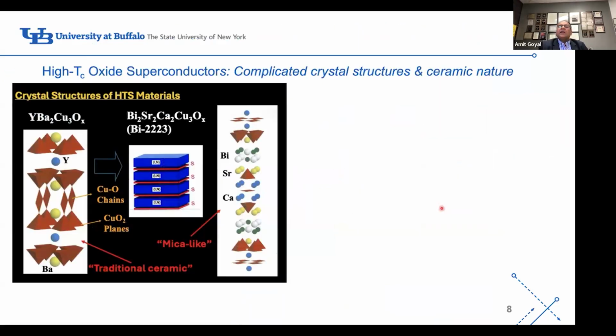Crystal structures of these materials. These are complicated materials. The so-called 90 Kelvin superconductor is yttrium barium copper oxide. It has one-dimensional copper oxide chains and two-dimensional copper oxide planes. It's got an yttrium atom at the center of the unit cell, two barium atoms, and copper at the cube edges. Then there are more complicated materials, this is called the BISCO, or the 2223, bismuth, strontium, calcium, copper oxide. You can think of them as charged reservoirs interdispersed with superconducting planes. The higher the Tc, the greater the distance between these superconducting planes.